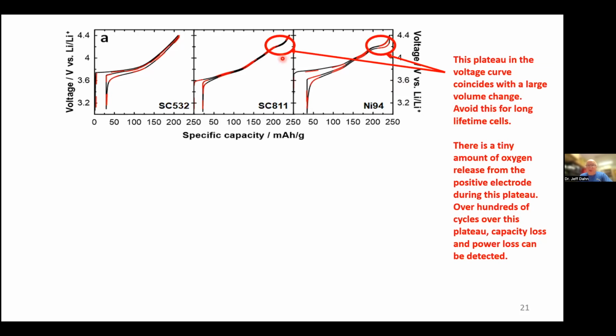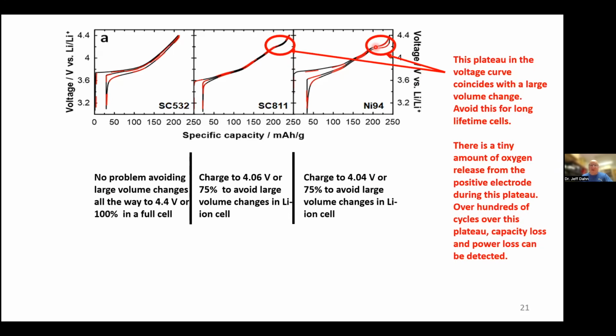And you could say, well, what if I make single crystal material? What happens then? Well, it turns out also that there's a tiny amount of oxygen released from the positive electrode during this plateau. And this oxygen can react with the electrolyte and cause degradation over hundreds of charge-discharge cycles, okay? So over hundreds of charge-discharge cycles, capacity loss and power loss can be detected. So if you want to really maximize battery life, you want to avoid this plateau. So what do you do? Well, all you have to do is stop the charge before you get to this plateau, which means charge to 75% to avoid large volume changes and this oxygen release.